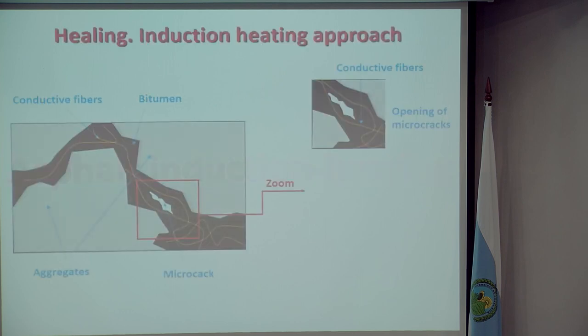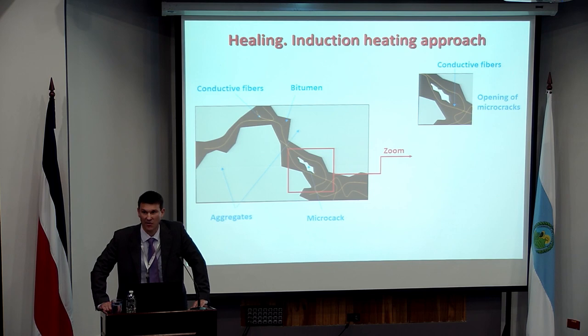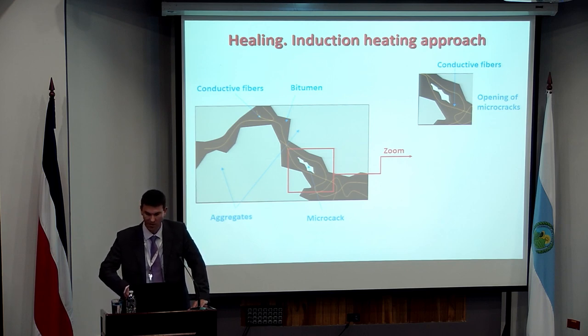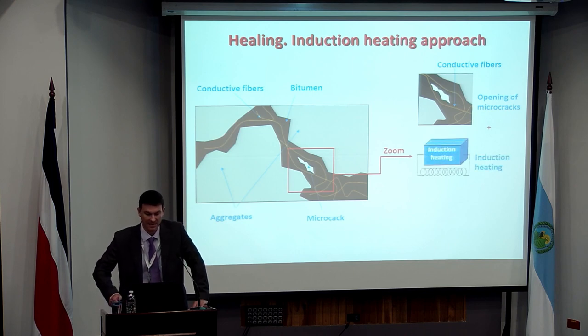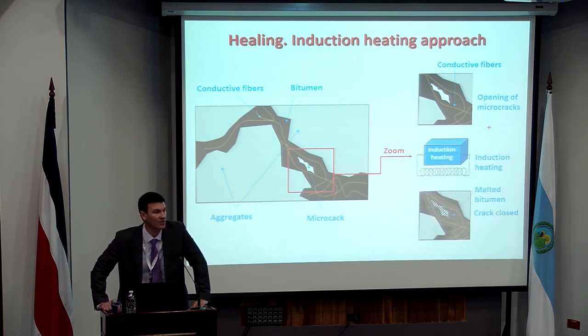So how does it work? Well, it works only if we have an induction material, or a material that can be heated by using the induction heaters. So any kind of metallic material, preferably some kind of waste material rather than something that we've had to manufacture, if we can place it inside our asphalt material, inside the bitumen or inside the mastic, we can locally heat it and we can use exactly the same phenomena that the bitumen already has to self-heal. So apply some form of induction heating and allow that crack or that area of weakness to close up.